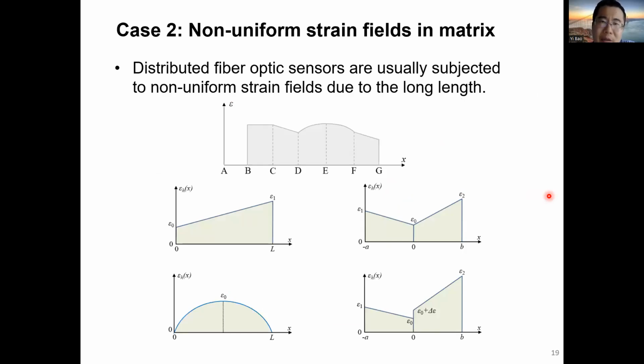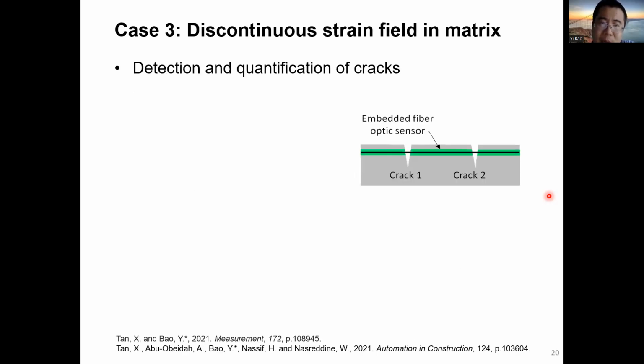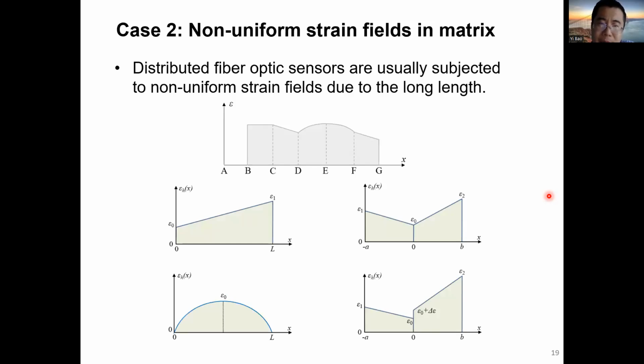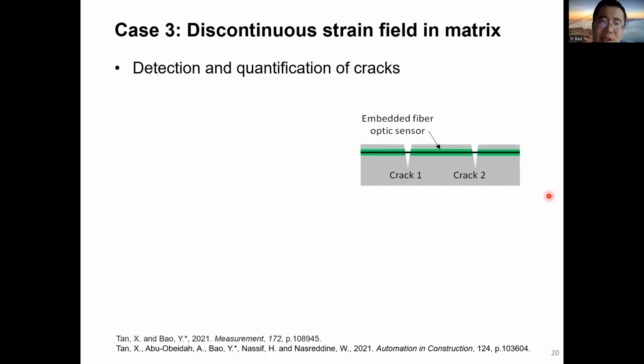But how about non-uniform strain fields? Because distributed sensors are very long, and at each length, the strain could be different. And this could be very complicated strain field in general. So solving this problem was a challenge, and my group solved this problem by representing the arbitrary strain field using a mathematical formula, and we solved this problem. And this work has been published. Based on this work, we were able to use a distributed sensor to measure continuous strain fields.